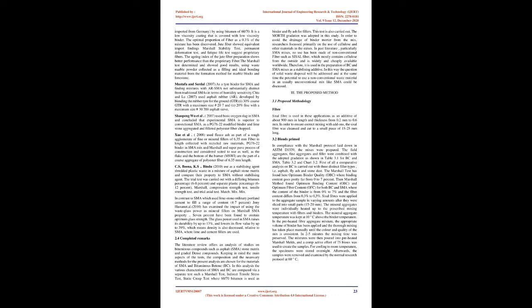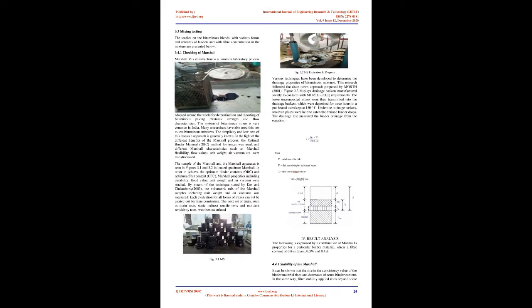Therefore in hot weather SMA is preferable. The usage and re-examination of fiber modified binder by cellulosic fibers, PG-65-22, with fiber ratios of 0.2%, 0.4%, 0.6%, and 1.0% in the weight of aggregates showed enhanced rheological results. Muniandi and Huet, 2006, used cellulose oil palm fiber (COPF) and found fiber modified binder. The PG-64-22 binder has been found to be able to be altered to grade PG-70-22. The fatigue efficiency of SMA mix has been improved by the use of cellulose oil palm fiber. Fatigue grew to a maximum fiber content of about 0.6%, while tensile stress and rigidity showed a similar performance pattern.